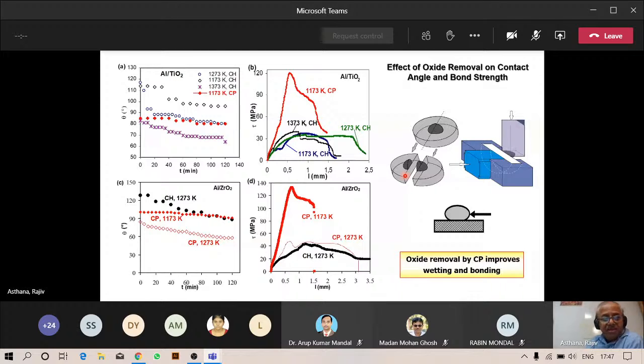So what you're seeing here is, again, the effect of temperature. If you were using capillary purification method, that is squeezing a droplet out of the capillary and then contacting the alumina or titanium substrate, you would see very high bond strength even at a temperature like 1173 Kelvin. If you do contact heating and then do the bonding test, the graph is somewhere here. So again, this is because you are able to remove the surface oxide of the droplet. That is why you get high bond strength. We see the same behavior with aluminum zirconia system.